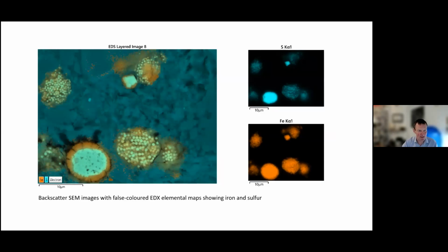And what you can see in the left-hand image is a framboid towards the bottom that has an orange rim where the iron is remaining, and a kind of a greenish core where the sulfur and iron are remaining. So this is absolute unequivocal information that that framboid has oxidized from the outside and the sulfur has gone off and actually attacked the cement matrix close to the framboid. You can see holes close to it.